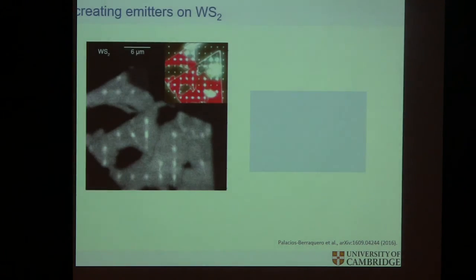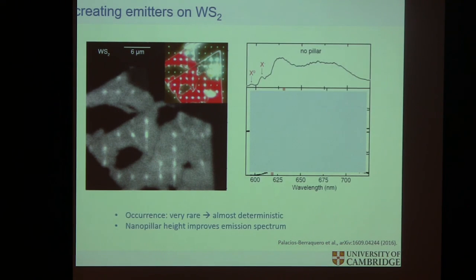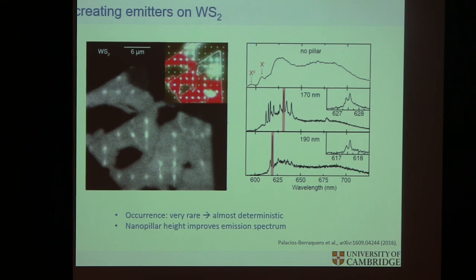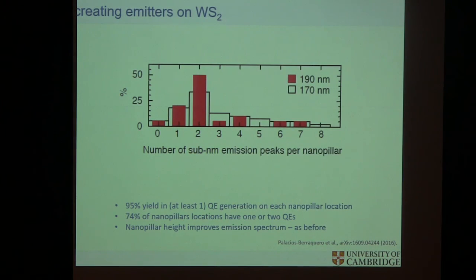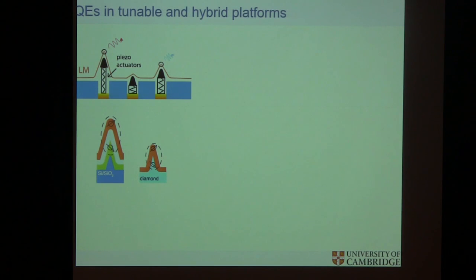And if you do this on different materials like WS2, you also get again the same feature of being able to create these quantum dots. So in that sense, again, very similar profiles. What it says is all you need to do to create these quantum dots at these locations is create a perturbation underneath. And we've done the most boring substrate you can imagine, silicon oxide.